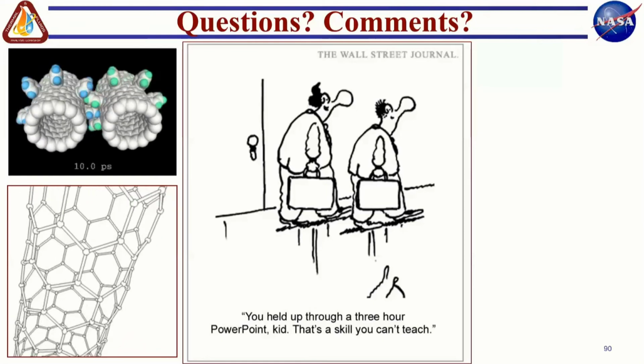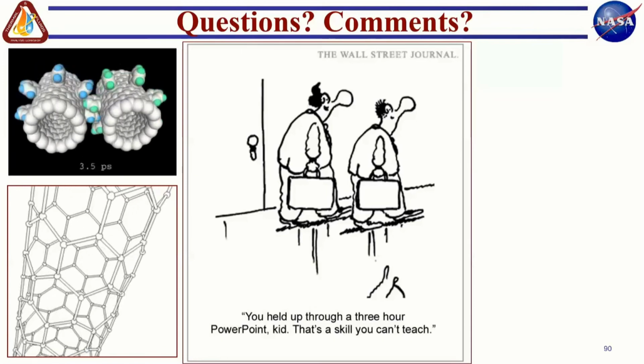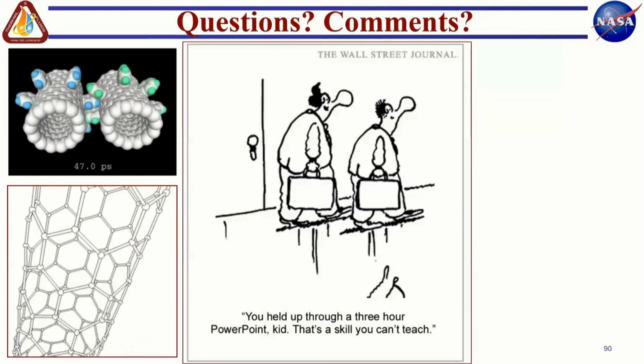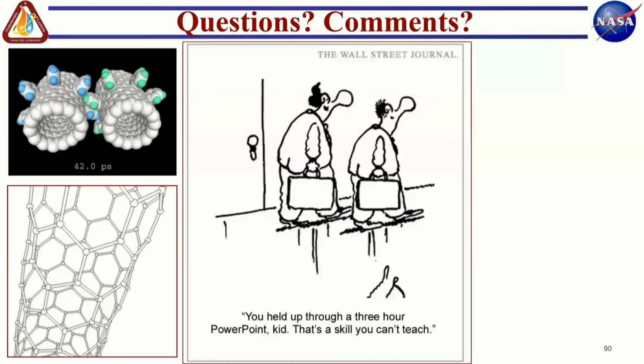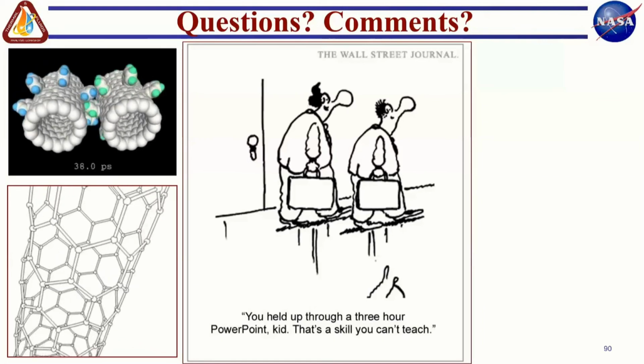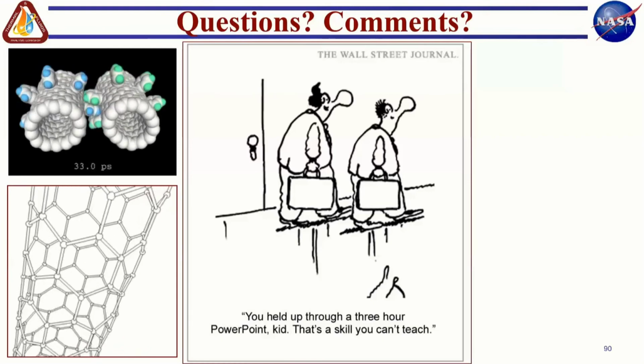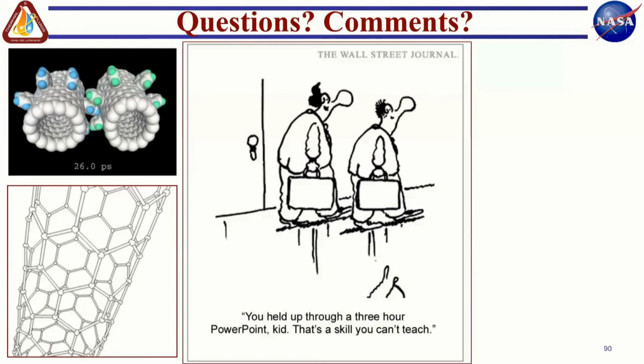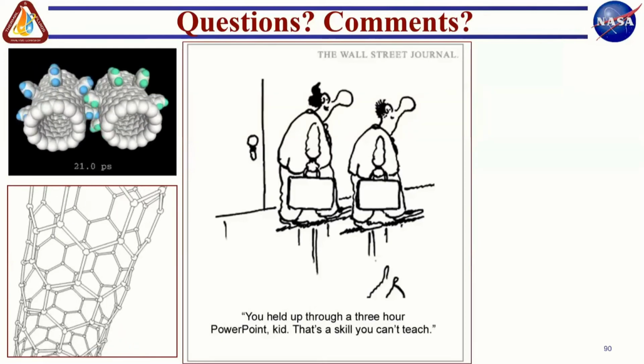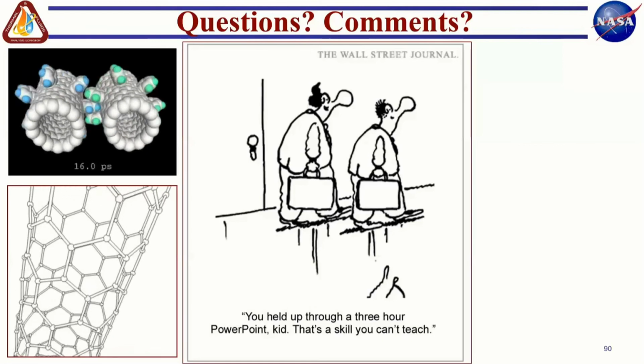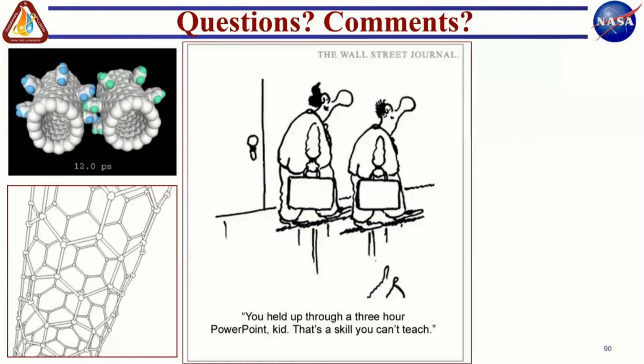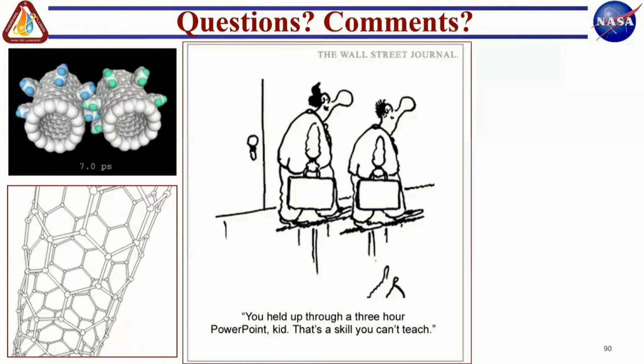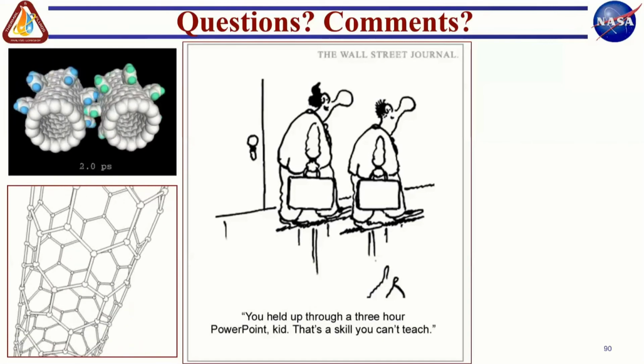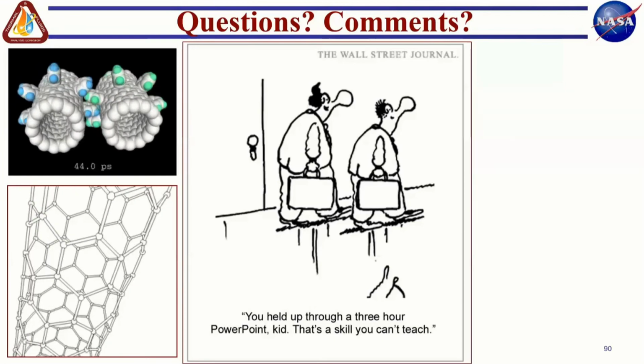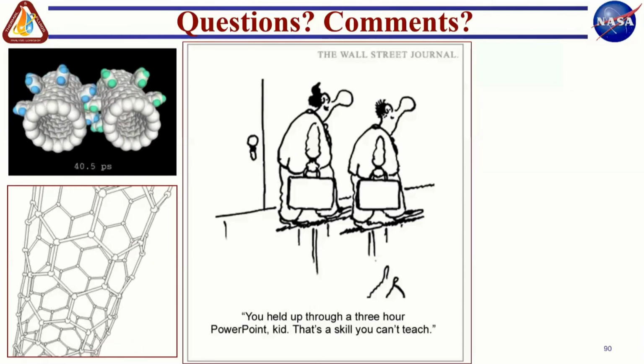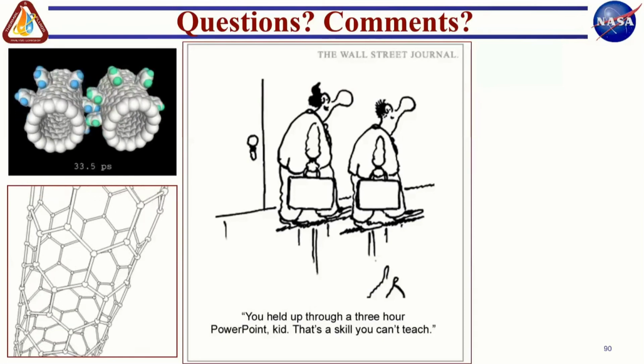But one benefit I see to microgravity is, nanofluid literature is replete with a lot of bad experiments where the nanoparticles were not stable in the solvent, and therefore they settled out and agglomerated over time, and people ended up with very controversial data. Particularly, you can trace it back to the stability of the nanoparticles in the coolant, and specifically because of gravity. So I would expect the nanofluids to work a lot better if you're looking at it as a coolant fluid or as a thermal storage, energy storage fluid. I would expect it to work a lot better in a microgravity condition compared to in Earth normal, or let's say moon gravity, or Mars gravity condition. So that's just a guess at this point.